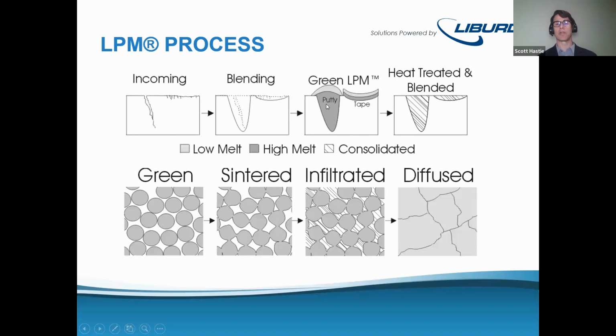And then we're going to put in our LPM material. So we have a high melt alloy, which is this putty that goes in first, and then a low melt alloy that goes in on top. So the putty is just like Play-Doh that you can form into those prepped areas, and then tape that you can roll out and spread across an area.